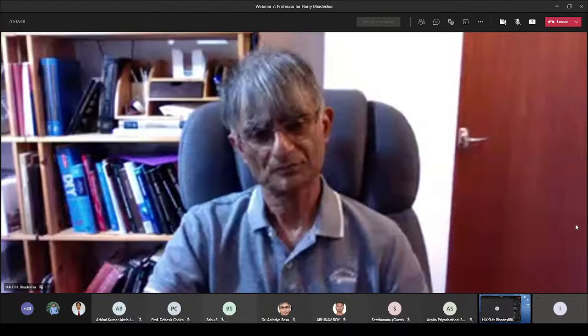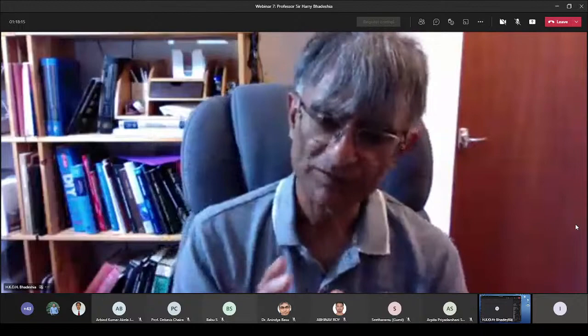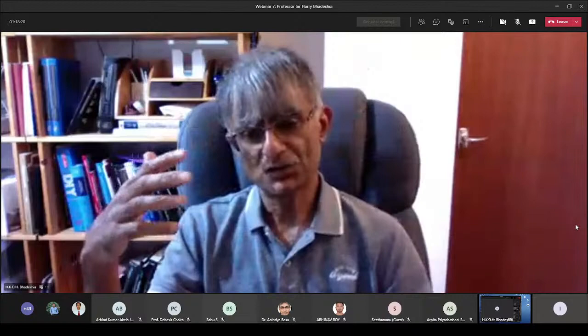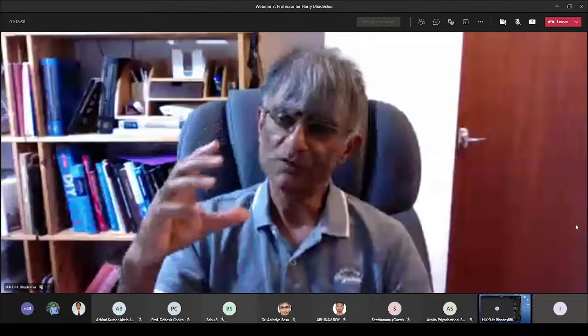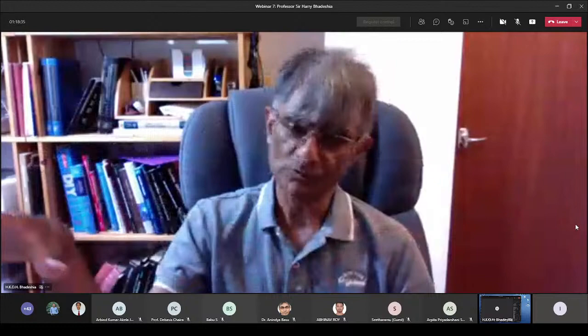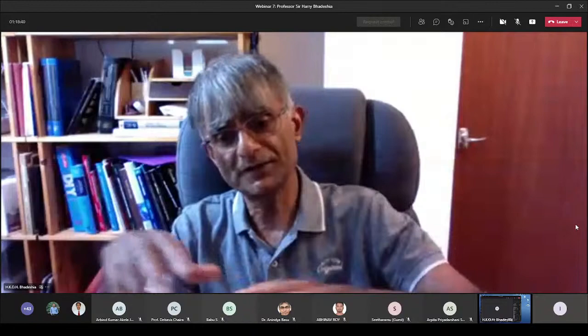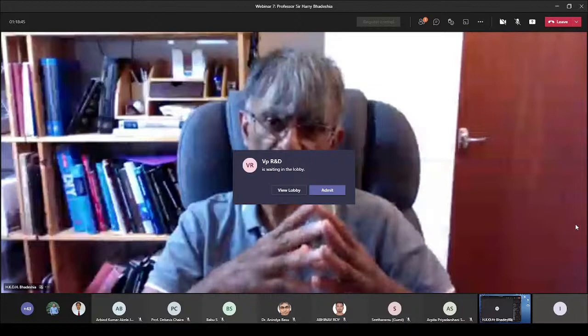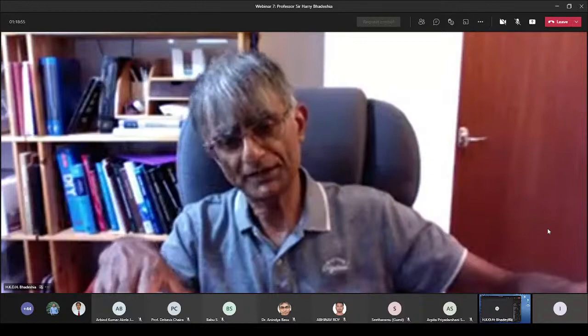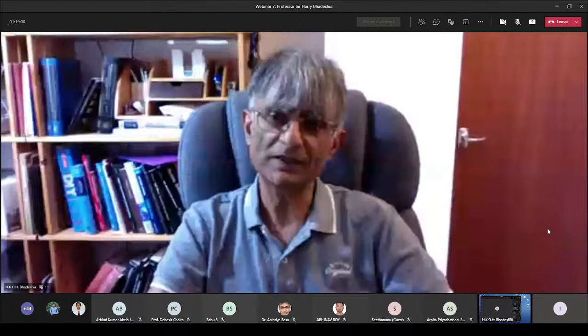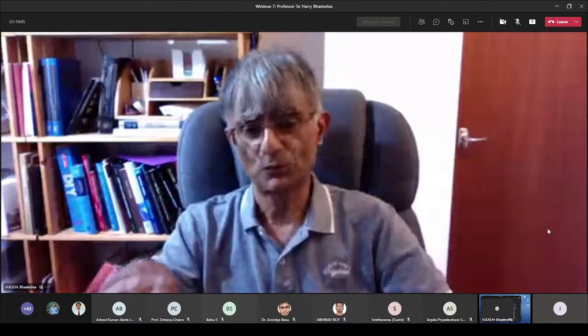This is actually a very complex question. Thank you very much for that. I have a colleague, Jai Jaiswal, who has a lot of experience in industry and in the rail industry. The things you need to consider are what sort of track you are interested in. Does it involve a curve? What is the radius of the curve and so on? The carbide-free Bainitic rail doesn't perform too well on a highly curved section of the rail. There you have to use pearlitic rails or other variants. There's a huge variety of commercially available rail steels for different kinds of scenarios on the route itself.